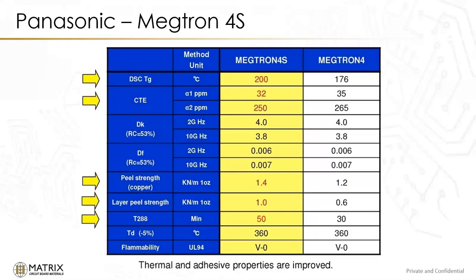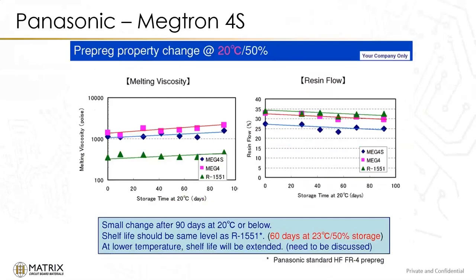So with all of these combined improvements, we get improved thermal and adhesive properties that allow it to handle the special sequential lams, the HDI buildups, and those types of designs now. With the change to the 4S though, there is a little bit of a shift on the prepreg rheology. The standard MEG 4 is the light purple there, and there's a slight shift with the MEG 4S as far as the viscosity goes, a little bit lower, so we're concerned a little bit with the storage time.